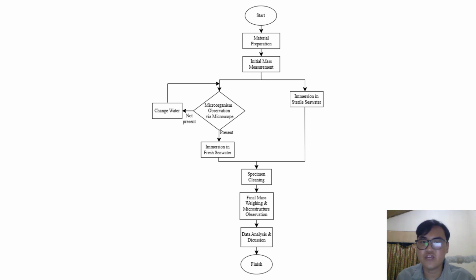After every period ends, which is 1 month all the way to 5 months, the immersed specimens were taken out of the water and cleaned by brushing. After ensuring the specimen has been thoroughly cleaned, it is weighed and its microstructure was observed. The weight data was then used to calculate the corrosion rate of the periods measured. After the last period group of specimen data has been collected, the data was analyzed and used to conclude this study.